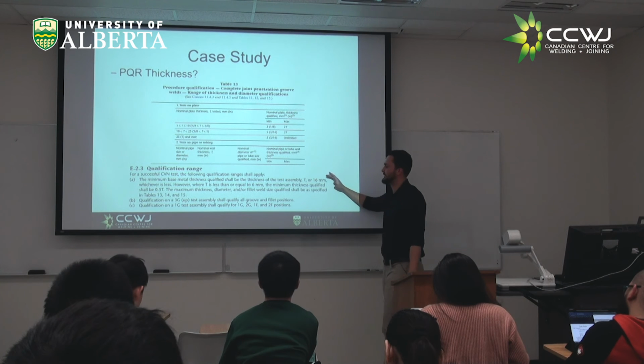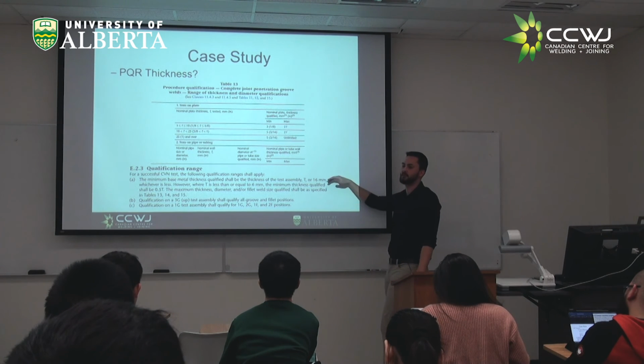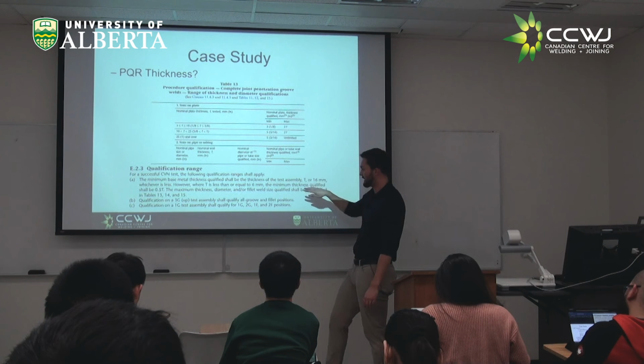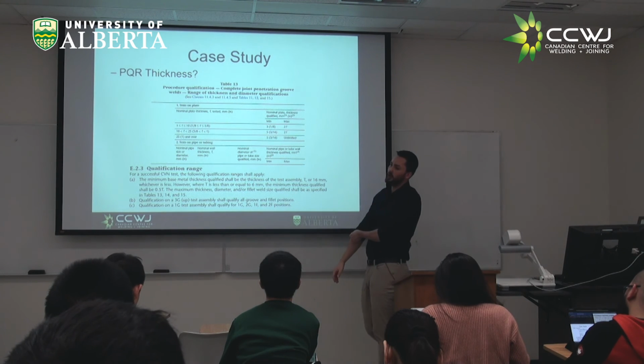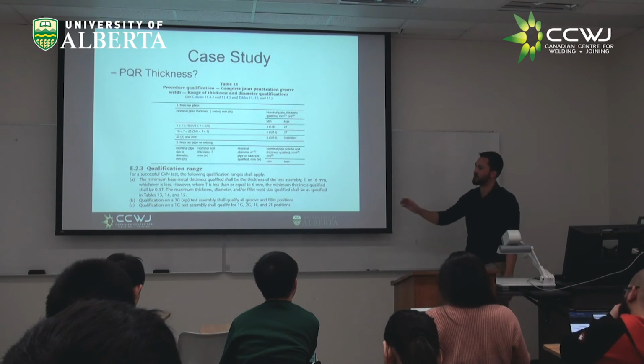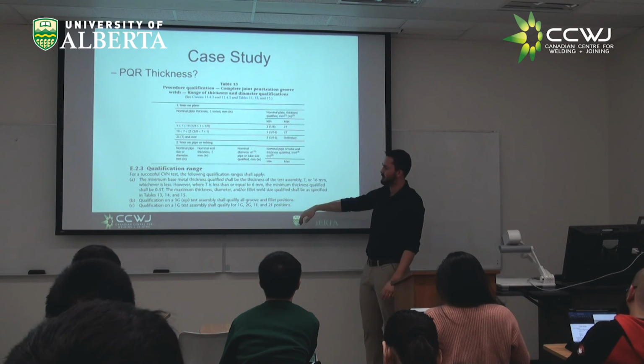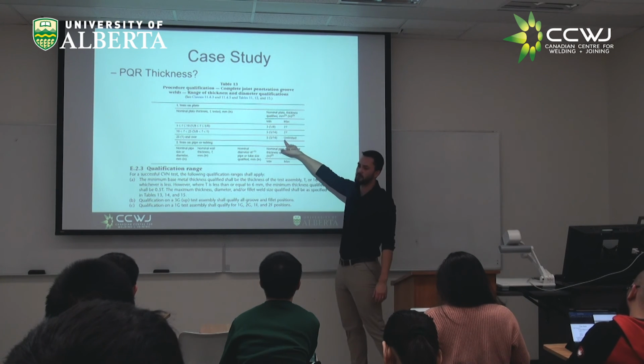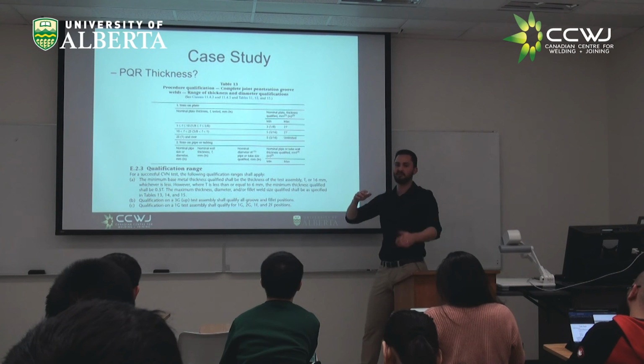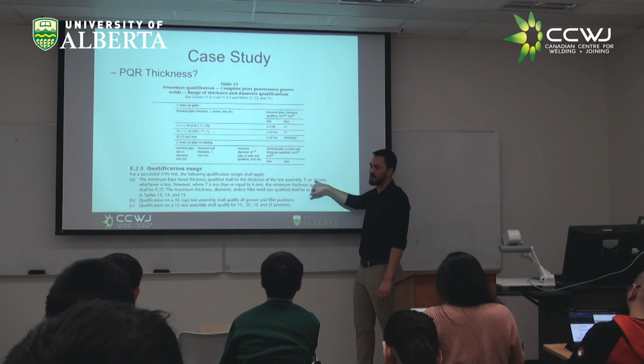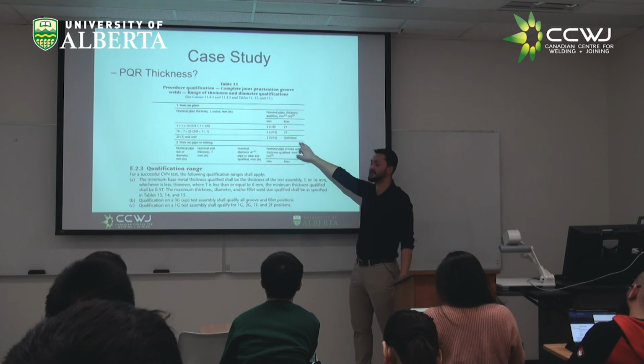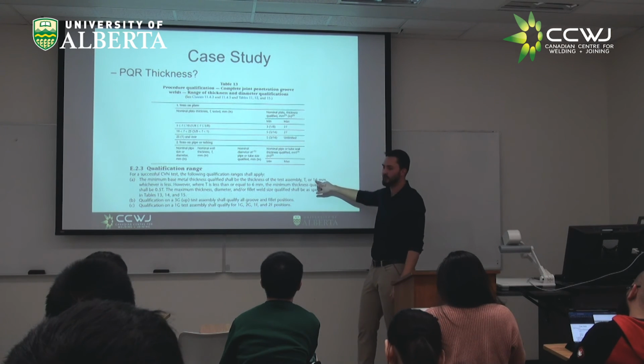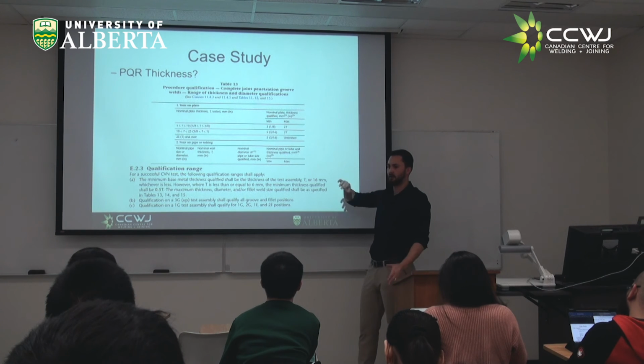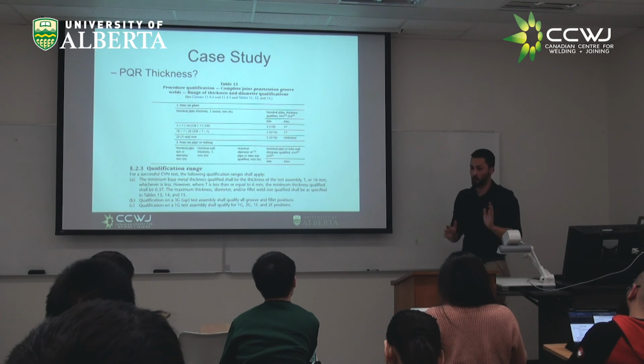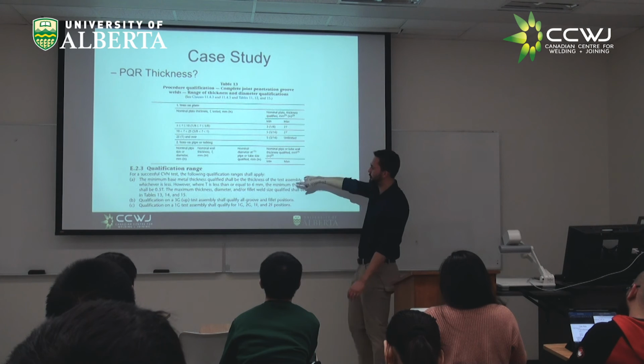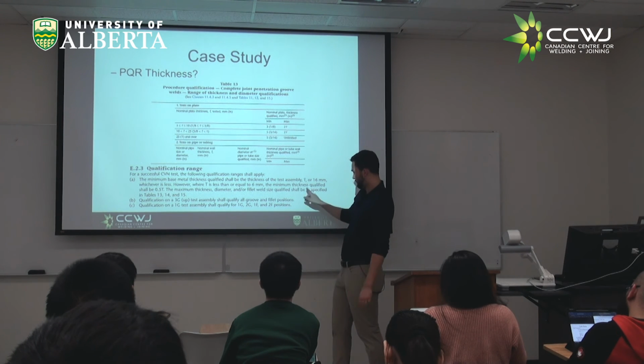Sounds great. But then they put this nice little thing in there in the actual annex that talks about CVN testing, and it says essentially you're limited by what the sizes are. So you don't get all of those tests. What they do is they essentially eliminate it from 16 to unlimited. So if you do a 25 mil test, our plates are 14 mil and 40 mil in this example. You do a test on 25 mil, under this it would cover all of it, but under this stipulation, you only get from 16 mil to unlimited. So you wouldn't be good for your web plate, right?